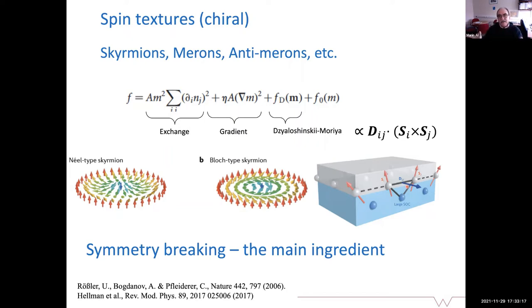The main ingredient for the Dzyaloshinskii-Moriya interaction to occur is a symmetry breaking. So the interface is a normal symmetry breaking element. But if you have a non-symmetrical, crystallographically speaking, broken inversion symmetry crystal, you may have big chances to get this Dzyaloshinskii-Moriya interaction in the bulk and then generate this skyrmion phase. And that is exactly what is happening with these skyrmionic crystals.